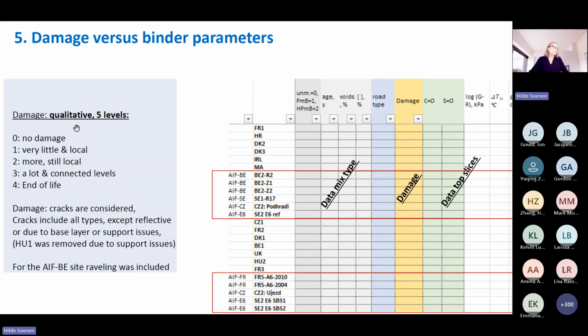And regarding the damage, we were inspired by this consultant, and we also decided to use 5 qualitative levels. So we had a 0 with no damage, 1 was then very little and local, 2 is more but still local. Here you have to change from local to connected levels, and 4 was end of life. And in this evaluation, we considered all types of cracks, except if we knew that they were reflective cracks, or if there was a base layer or support issue. Because of that, 1 section was removed. And for this Belgian section, we also included raveling as a damage parameter.